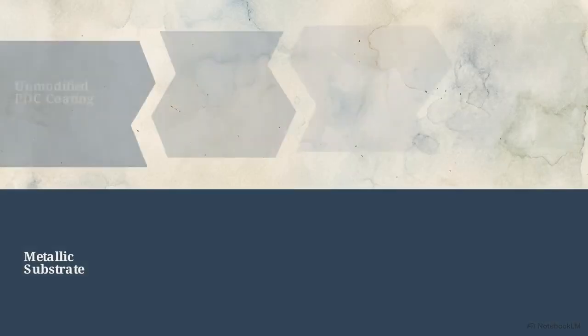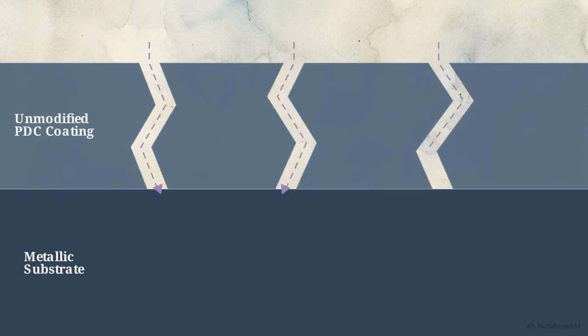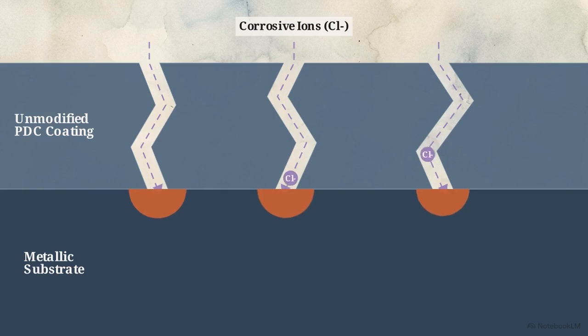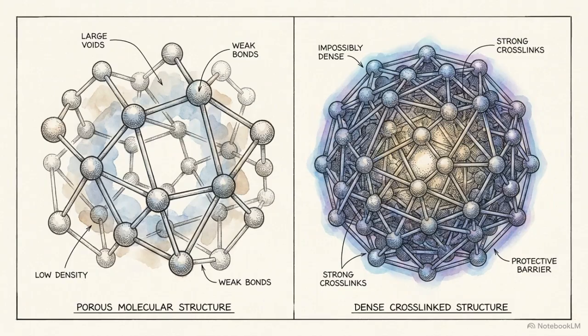Unmodified PDC layers often fail in these conditions. Shrinkage-induced microcracks create direct pathways for corrosive ions to reach the underlying metal. The solution lies in chemical modification. By reacting the polysilazane precursor with MTES, engineers can increase the cross-link density before the pyrolysis phase begins.